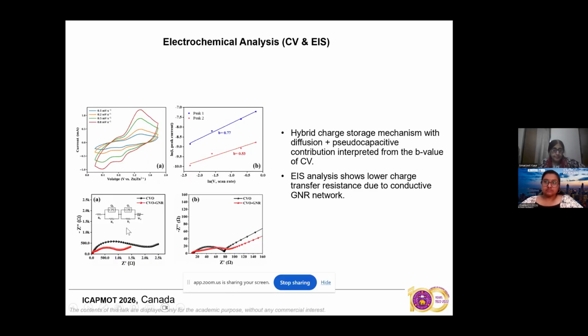So now looking at the electrochemical analysis of these materials, one can see that we have used a non-aqueous electrolyte, because it has been observed from previous studies that most of the vanadium-based materials tend to dissolve in the dilute aqueous electrolyte. So that is why we have used the non-aqueous electrolyte.